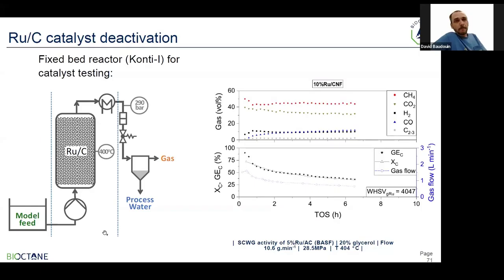Next slide, please. So here you find typical results obtained from the tests done on this lab scale setup. We find on one side the gas composition, of course, and the gasification efficiency, so the quantity of carbon found in the gas phase with regard to the amount of organics fed in, and also the conversion of the organics present in the feedstock. Next slide, please.